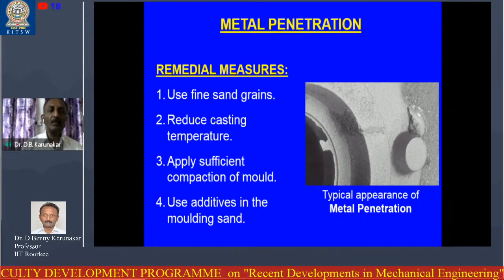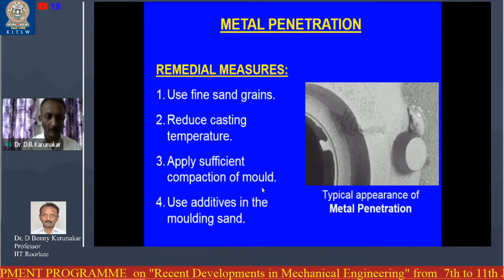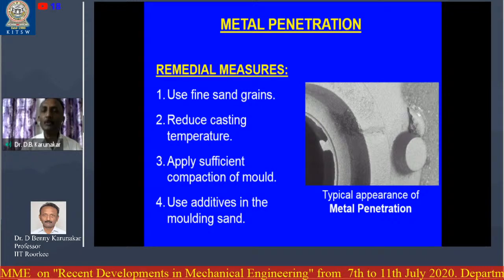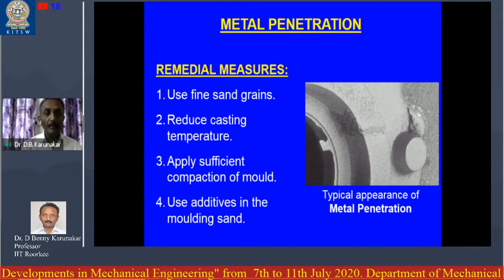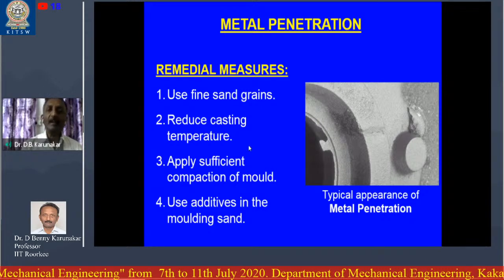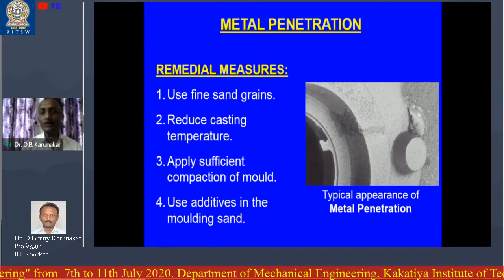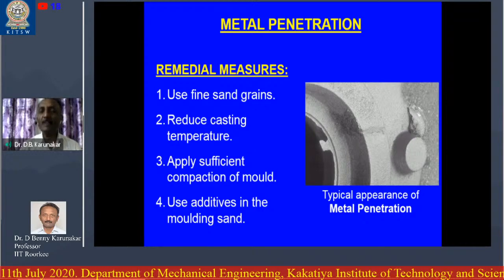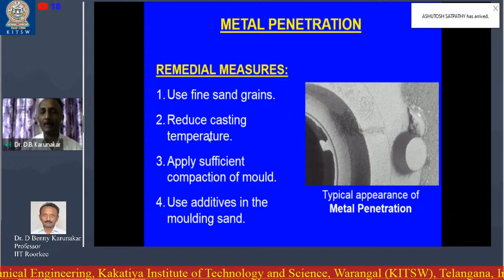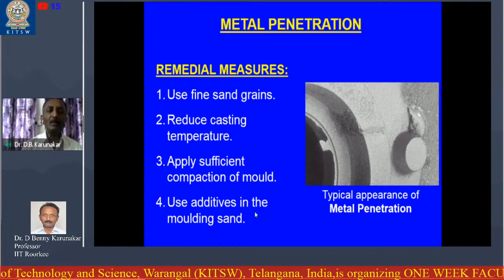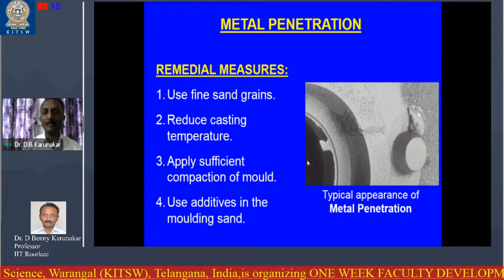How to prevent this? Use fine sand grains. You should not use coarse sand grains, but it doesn't mean the sand should be too fine. What will happen if it is too fine? The permeability will come down. Also reduce casting temperature, apply sufficient compaction of the mold, and use additives in the molding sand.